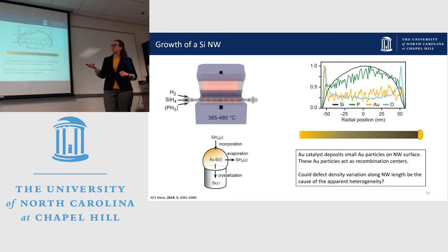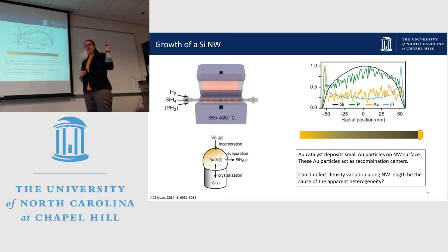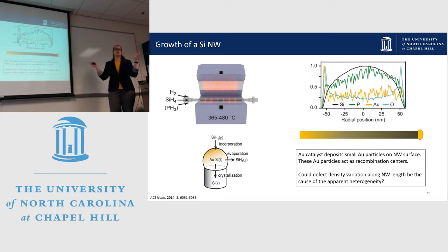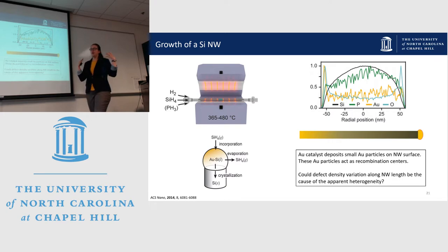And the way it works is you have a gold catalyst and you heat it up very hot, it becomes molten, and then you flow silane gas through the furnace. The silane dissolves in the gold, and a silicon nanowire sort of crystallizes out, right? So it grows up like this, like a tree. And what can happen is as it's growing, some of the gold from the catalyst can be deposited on the nanowire surface, right? So you might think, well, maybe more gold gets deposited, say, early on when the growth isn't as stable yet, right? Gold is a really good recombination center, so you would have faster recombination in a region that has more gold, for example.